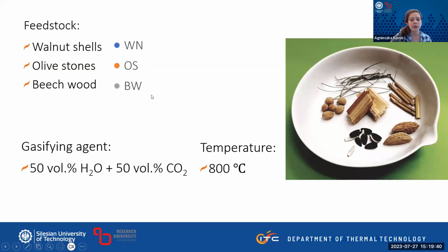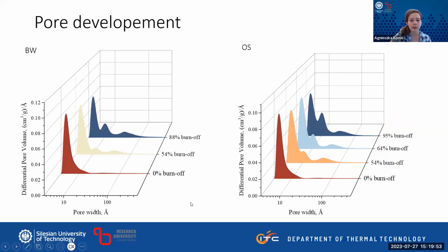And besides walnut, we also prepared the char from olive stones and beechwood, because, as I mentioned, they had a promising pore distribution even in the pyrolytic chars. After the gasification, you can see that in both samples, the porosity was developing quite nicely, even including some mesopores. So they looked pretty good.